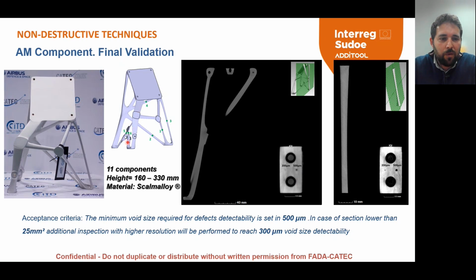And then there were, as I said before, more critical areas or regions of the component that had to be inspected in high resolution. So as you can see here, for instance, the 200 microns defect, it was observable. So it's an indicator that your inspection was performed correctly.